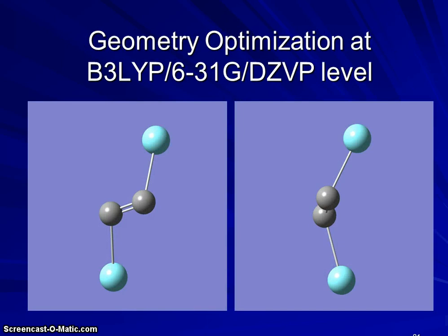But when we performed molecular modeling calculations on this, we found that the lowest energy configuration was not a perfect cross, but the carbide tilted and out of plane from the yttrium. And so this was unexpected, and we ran the calculation several different times with several different starting geometries and found that.